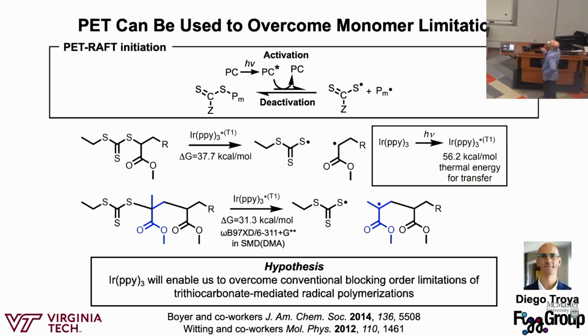So the idea is that you can have your photocatalyst, and then you can choose your photocatalyst to excite with light, and then according to either the energy transfer or the reduction potential, you can pair it with the chain end where you can get this activation, deactivation. This initiation pathway is distinct from that chain transfer pathway, right? Because we're just directly activating our chains with the catalyst. We're not going through that chain transfer.